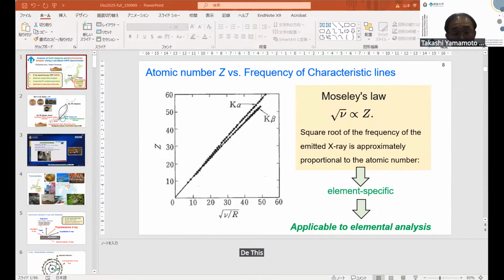Then this energy is element specific. This plot shows the atomic number Z plotted as a function of the frequency of the characteristic X-ray lines. This is Moseley's law. Moseley found the square root of the frequency of the emitted X-ray is approximately proportional to the atomic number. It shows the energy is element specific. Then the characteristic X-ray can be used for elemental analysis.